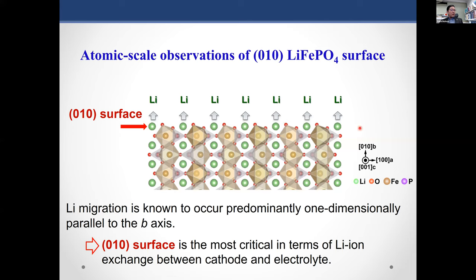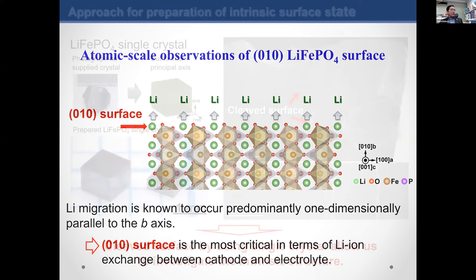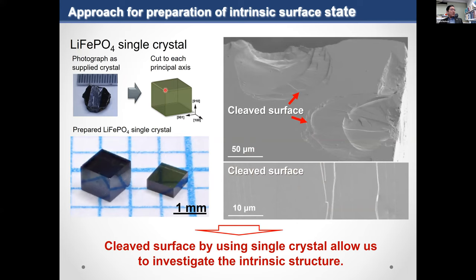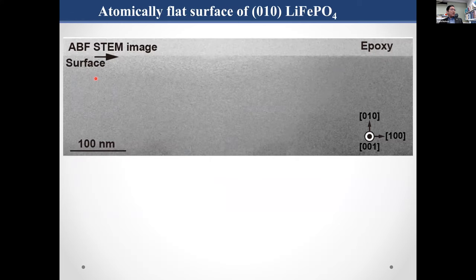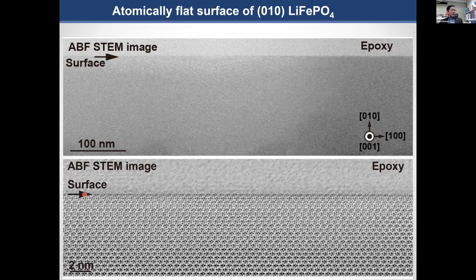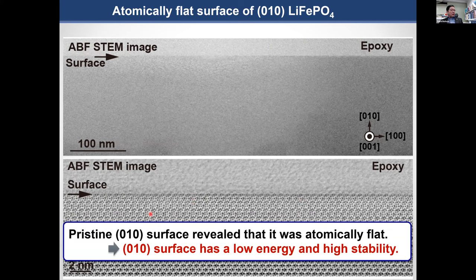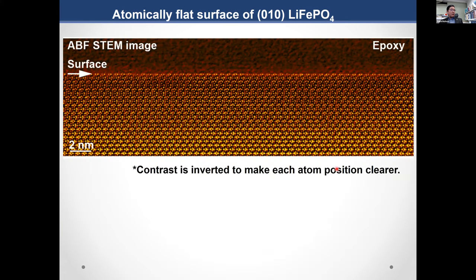So we observed this surface from the cross-sectional direction. We prepared iron olivine single crystals, and this is the 010 surface. We cleaved this surface and immediately protected it with epoxy. The fresh surface is observed directly from the cross-sectional direction. This is the thus obtained ABF image, with epoxy covering the surface. This is a magnified ABF image. You can see an atomically flat surface. This is profile imaging, and it indicates that the surface has low energy and high stability. You can see all atoms, including lithium and oxygen. To see each atom more clearly, the contrast is inverted to make each atom position clearer and see the surface structures.